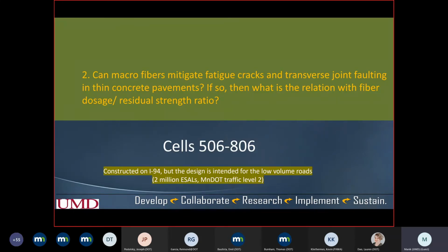Question number 2: can macro fibers mitigate fatigue cracks and transverse joint faulting in thin concrete pavement? And if so, what is the relation with fiber dosage or residual strength ratio? In order to get the answer to these questions, we will focus on the results of cells 506 through 806. And I would remind you, these were constructed on I-94, but the design is intended for low volume roads. The design thickness is only 5 inches, which is definitely not typical for an interstate pavement. 2 million is also MnDOT's low volume road traffic level 2 category. So let's say the design is 2 million.